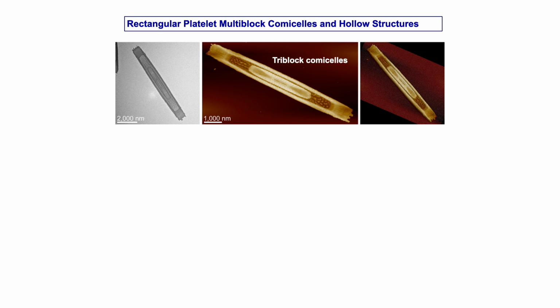If you add polymers with different corona-forming blocks that have different chemistries, for example they can have a different fluorescent dye attached, you can again build up block structures, but now they're two-dimensional block structures. So this is a 2D block co-micelle where we've done sequential additions of different polymers to the seeds, and here's an image by atomic force microscopy.